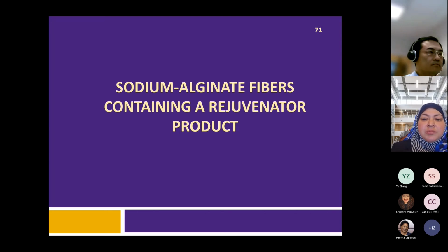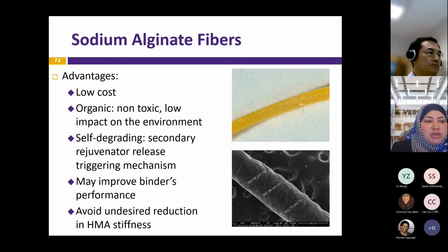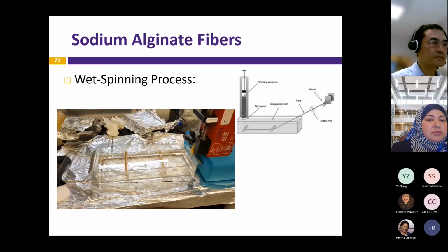Another mechanism that we developed in order to encapsulate the rejuvenator product or the healing product is sodium alginate fibers. You can see the sodium alginate fibers right here in the pictures. Why sodium alginate? It's an inexpensive material. It's organic and non-toxic, environmentally friendly. It degrades over time. So when it degrades, then it's going to slowly release the rejuvenator, reversing the aging process by itself. Also, it's an elastic material, so it might even improve the mechanistic behavior of the asphalt mix.